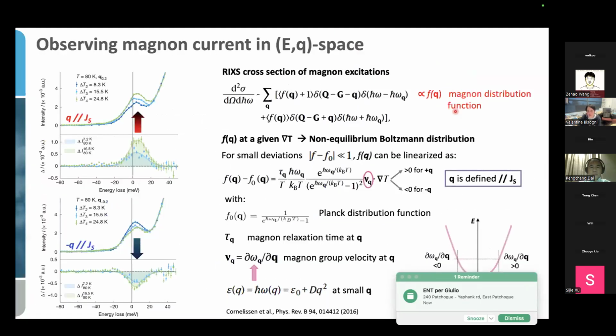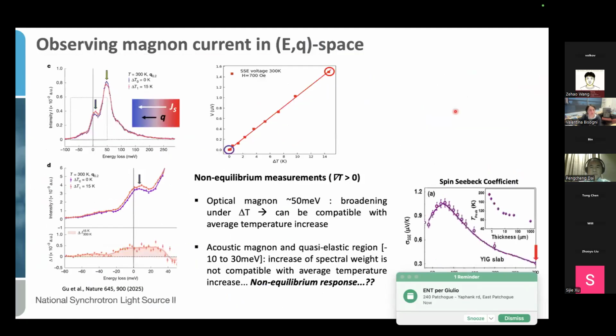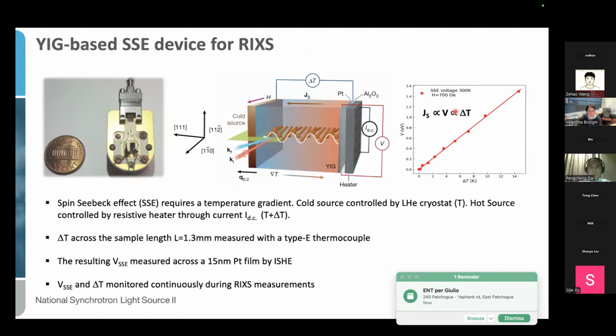Thanks. So I have several questions, Valentina. The first question is, in the real spin Seebeck coefficient measurement, you would also need to apply an external magnetic field, right, to align domains. Have you done that in your measurement? Yes, for two reasons: to saturate the magnetization of our little crystal, and to measure the spin Seebeck voltage by the inverse spin Hall effect. So we had, let me go back, excuse me, okay, there it is, H.